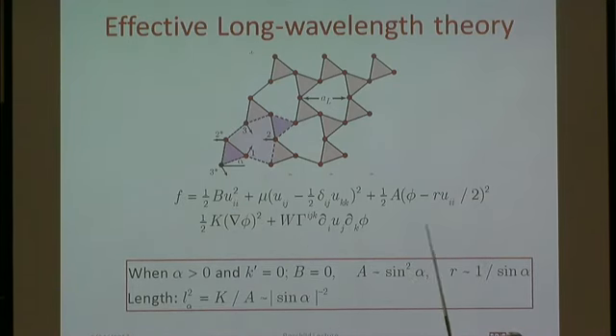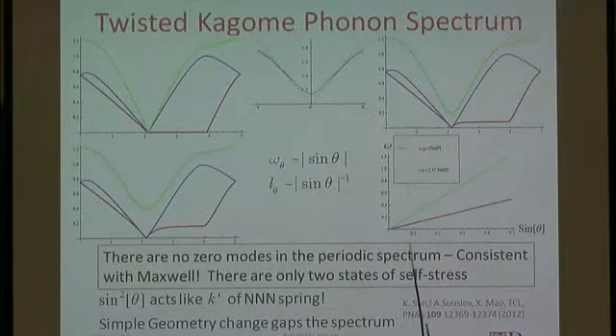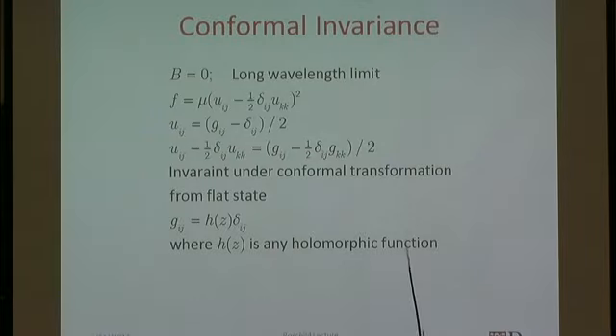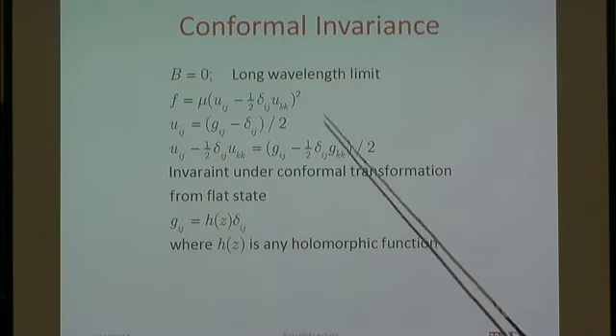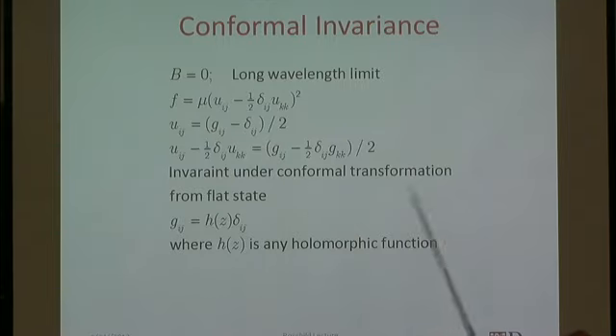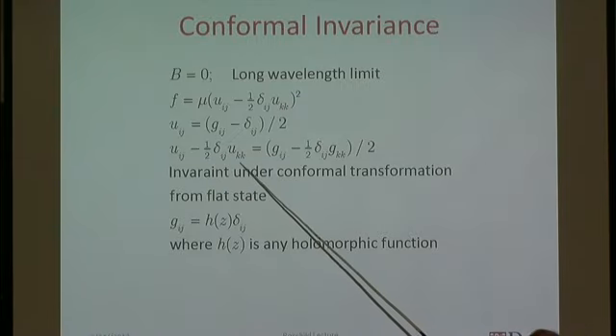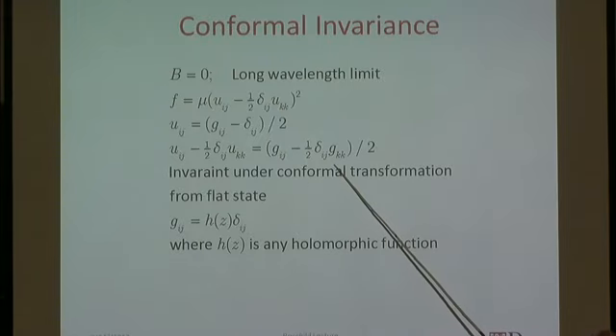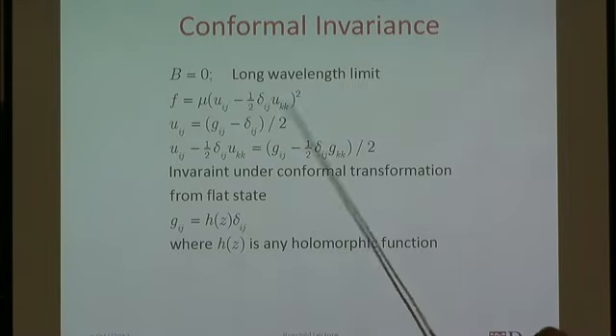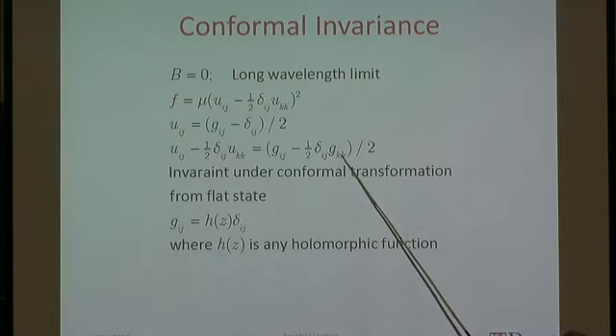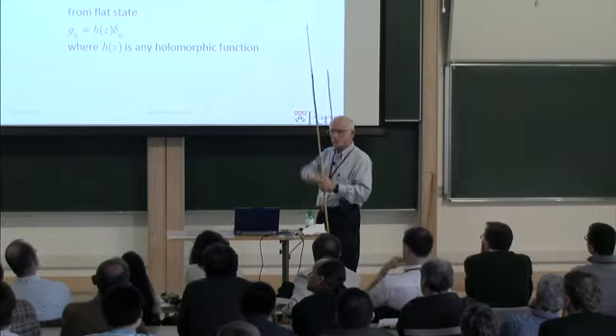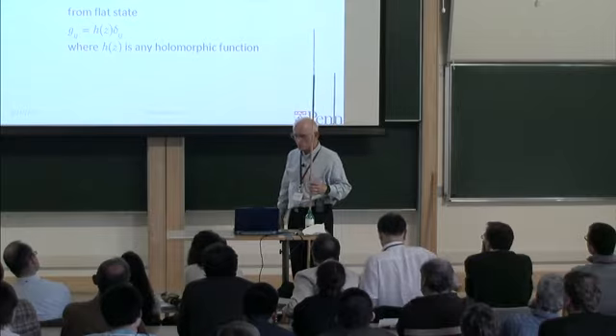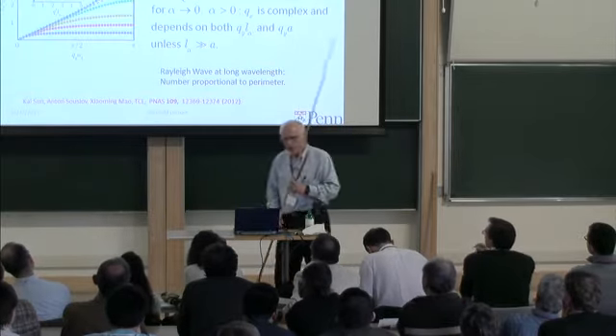this is non-vanishing. And I've got a theory, once I've relaxed everything, which is, I'll just say this now and go back to it, in which the bulk modulus has vanished. All I have is the symmetric traceless part of the strain tensor, and this has the property that the symmetric traceless part of the strain tensor is the same as the symmetric traceless part of the metric tensor. So the energy doesn't change for any distortion that leaves this unchanged, and any distortion that leaves this unchanged is a conformal transformation. So this is a conformally invariant field theory, and you can do all the tricks that people do of looking at strips and so forth to determine what the zero modes are. But let's go back and do what the calculation is.